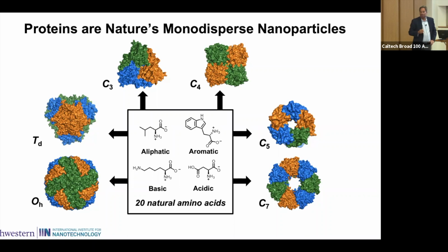The really neat thing about moving from inorganic particles to proteins is that I can't uniformly modify inorganic particles with bonding elements. With proteins, one is I get greater monodispersity. I can make a mole of protein particles that are all the same. I can't make a mole of inorganic nanoparticles that are all the same above a certain size.